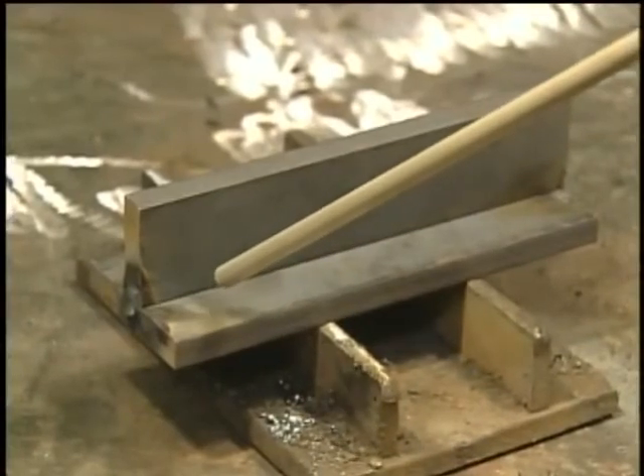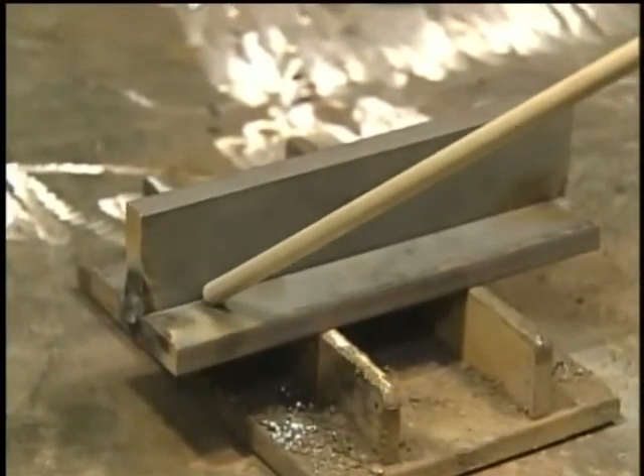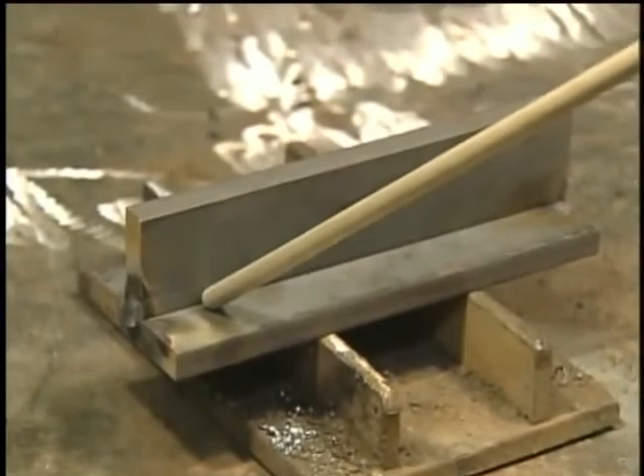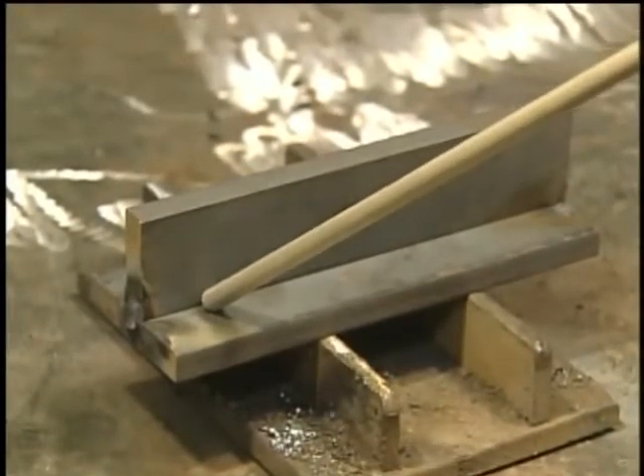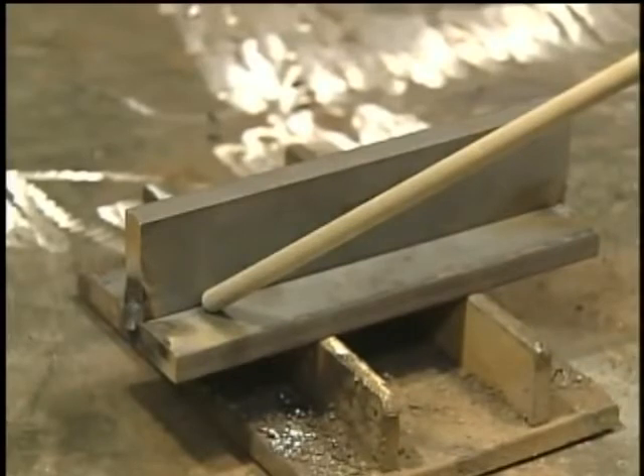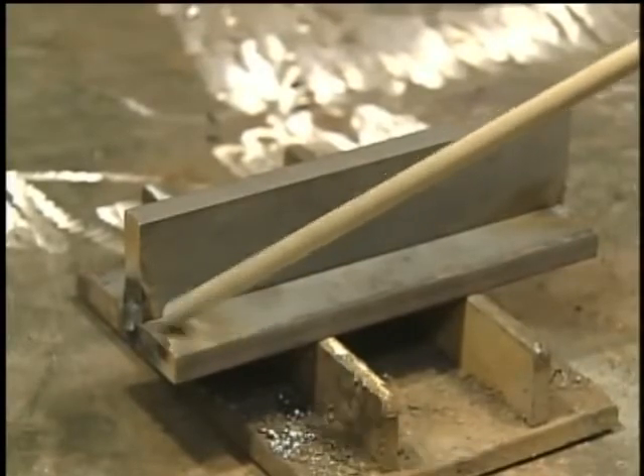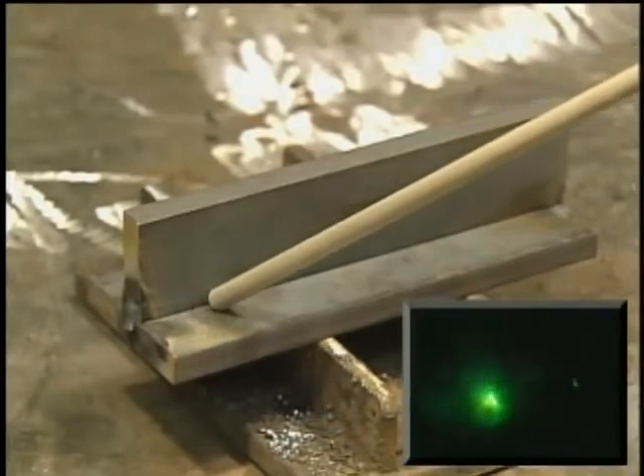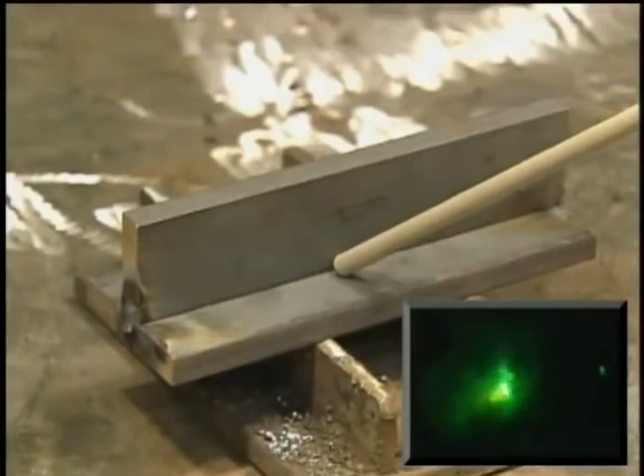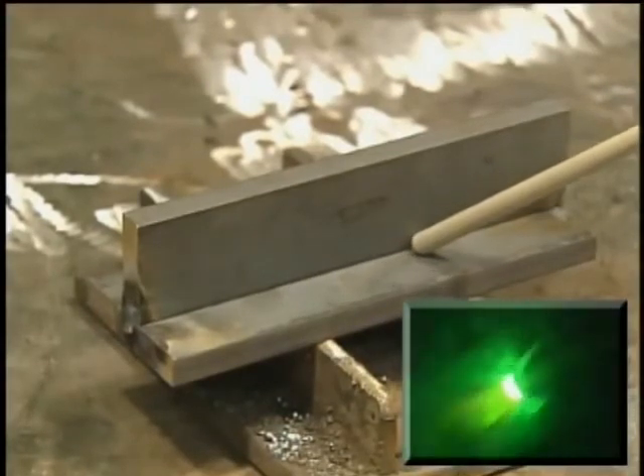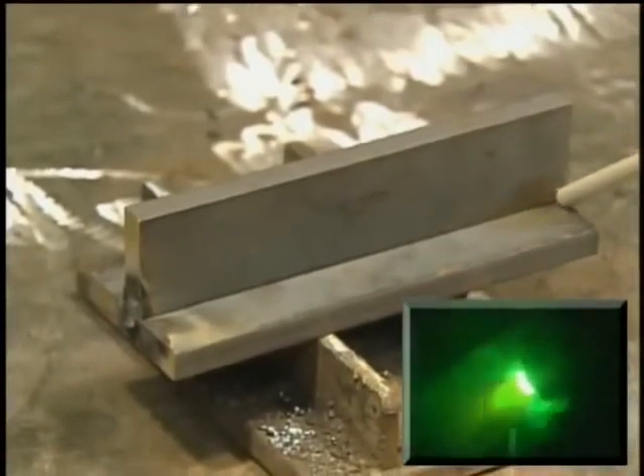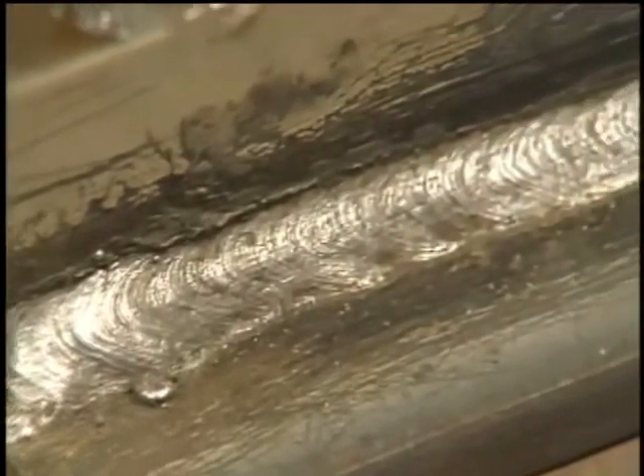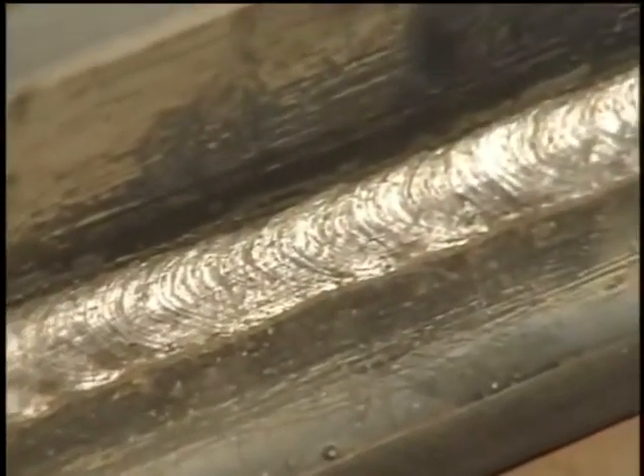For horizontal fillet welding, hold the welding rod at a 45 degree angle to each of the base metals. The welding rod should be at a 70 to 80 degree angle to the direction of the weld, with the tip of the welding rod just slightly touching the base metal. Check the bead width and height, as well as the undercut and overlap.